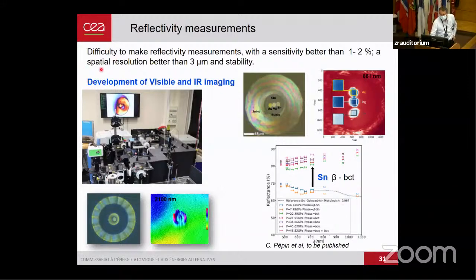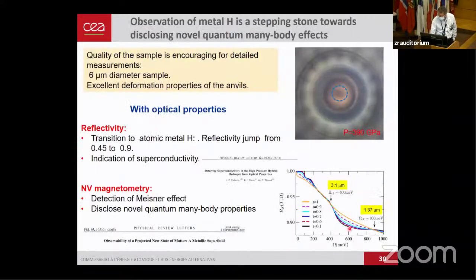The way we want to do it is to do imaging in the visible and infrared, and do reflectivity. To do accurate measurement is quite complex, especially if you want to do reflectivity measurements with a sensitivity better than 1 or 2%, which is needed to disclose this subtle change of reflectivity, and with a spatial resolution of better than 3 microns.